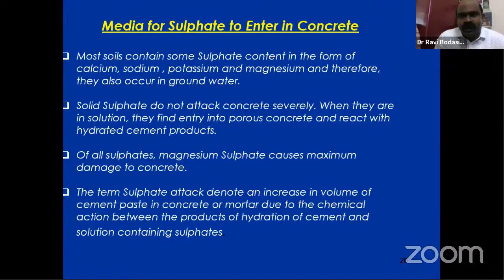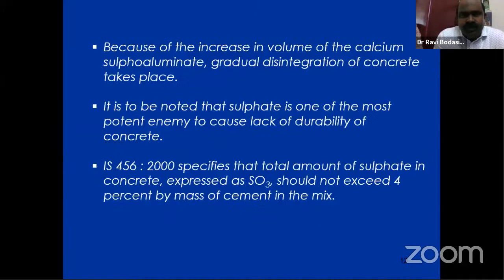You can see why, because when we are designing, we consider the ASC, the area of steel versus the area of concrete. If the bulging of concrete occurs because of the sulfate, then definitely the concrete surface will separate from the reinforcement. Because of this increase in volume, there is gradual disintegration of concrete as the sulfate attacks the reinforcement. The deterioration starts slowly, but after some period the effect will be more.